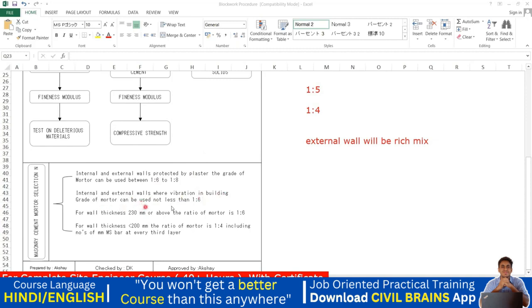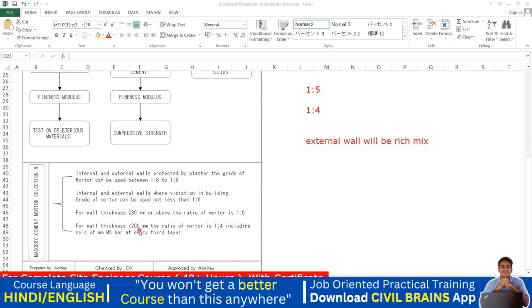For walls subjected to vibration — such as where machinery is present — the mortar grade should not be less than 1:6. For wall thickness 230 mm or above, the mortar ratio is 1:6. For wall thickness less than 200 mm, the ratio is 1:4. Since a thinner wall has less stiffness, a richer mix is used to compensate, and MS bars are also added at every third layer.